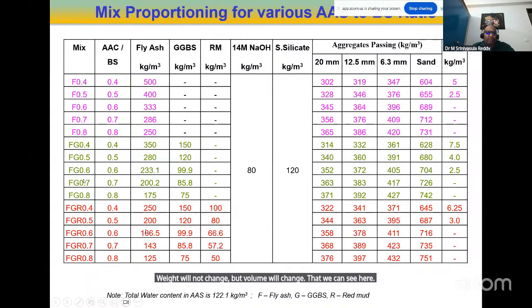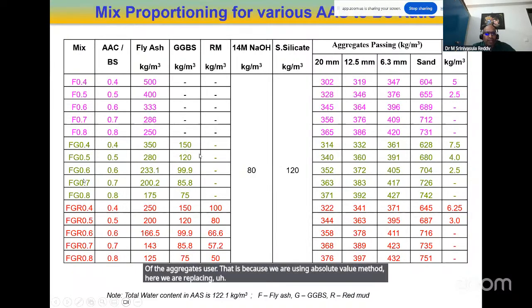Even though the total weight is the same, the aggregate we have used is also, maybe the same percentage, like 20 passing, example A%, B%, C%, D%. This remains the same for all the mixes, but you can observe here the variation in the weight of the aggregates used. That is because we are using the absolute volume method. Here we are replacing fly ash with GGBS.